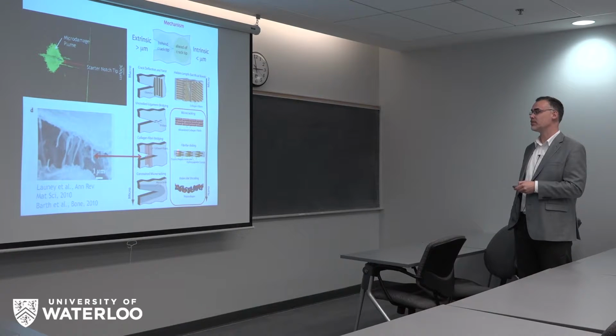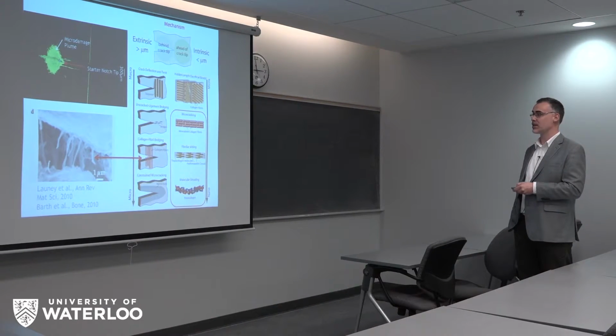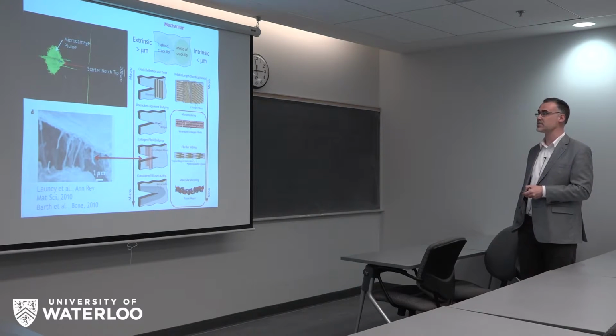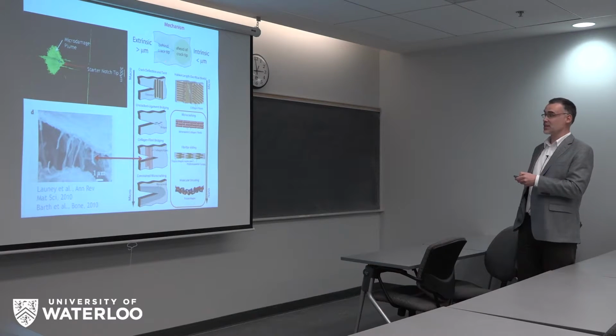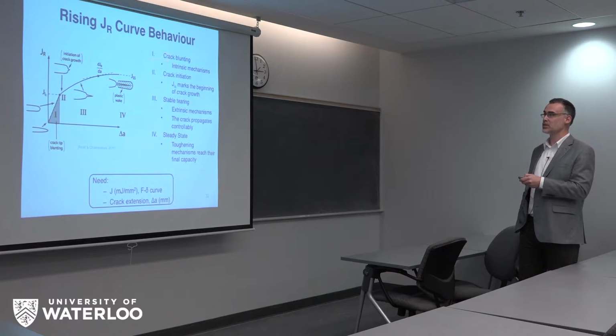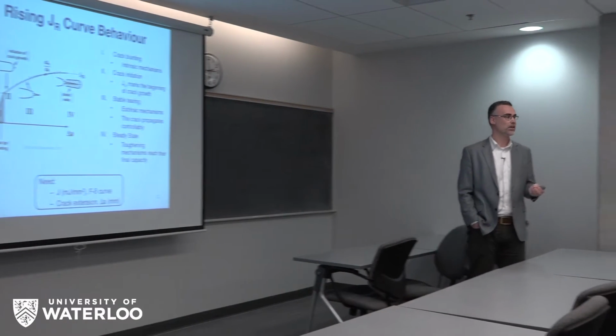And collagen, changes in collagen will affect both, we think, intrinsic mechanisms and extrinsic mechanisms. So the result of the extrinsic mechanisms is that you'll get what's called a rising R curve. Fracture toughness in a material like bone isn't a single point measurement. You don't just load it up and it catastrophically breaks. There will be a stage where you'll reach what's called J1C, crack growth initiation fracture toughness. And then the mechanisms within the bone will actually allow the crack to grow in a stable manner before you get catastrophic failure. And so we wanted to capture this rising R-curve behavior because it's relevant to how well bone or bone graft material can accommodate cracking and resist catastrophic failure.